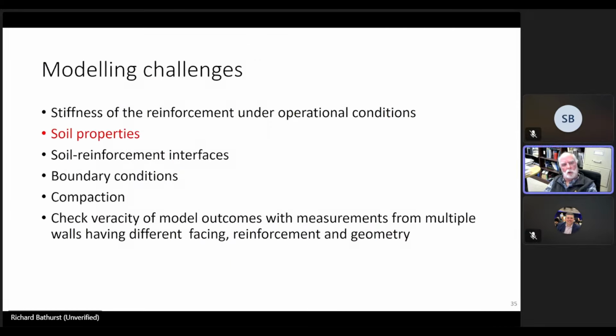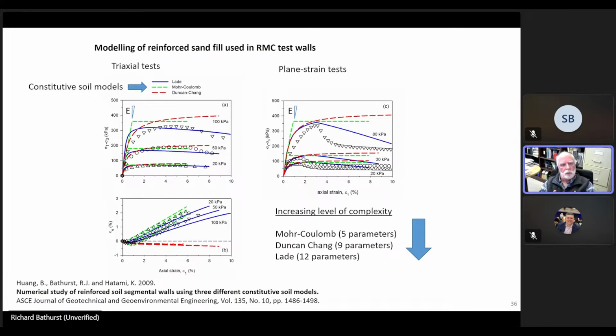Other challenges, soil properties, and this is not unique to MSE walls. Here, what you see are a series of triaxial tests and plane strain tests. And the triaxial tests are quite familiar to all of us, at least qualitatively. And one of the challenges with our granular soils is they're highly nonlinear and stress dependent, and you can see that in the curvature of the physical data.